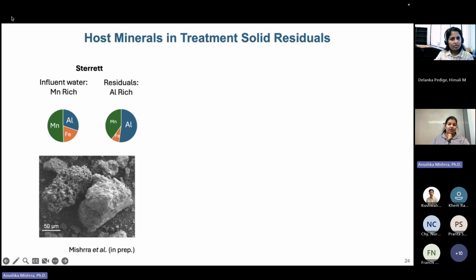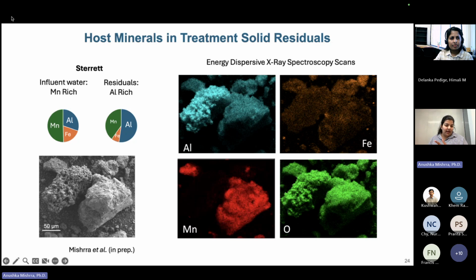We know from our ICP-MS data, like elemental mass based measurements, that we do have manganese, aluminum, iron, but what do these solids actually look like? So here's the picture I took for some of the particles collected from the site Sterret. The key difference is that influent water was very rich in manganese, but the residues actually started having more aluminum present in it. So that's interesting that we have now abundance of aluminum in them. At the same time, we also have manganese in it.